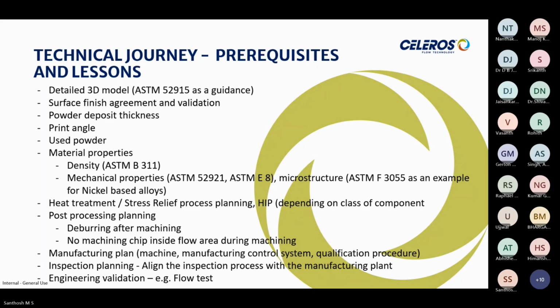We also need to be sure that there is no machining chip, as we also did grinding on this part, ID grinding. So we wanted to be sure that there is no machining chip or grinding debris that gets into the flow area. In this particular case, we agreed upon using a special soap which would close the holes. As I said, there are close to 1,000 different holes there, or windows, or flow paths, whatever you want to call it. The special soap was used on the inside and the outside, during the machining process. That soap would prevent any grinding wheel debris or machining chip from getting inside the part, and soap can be easily washed off after that.